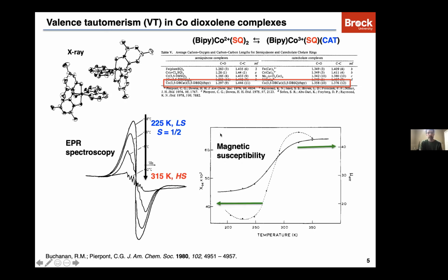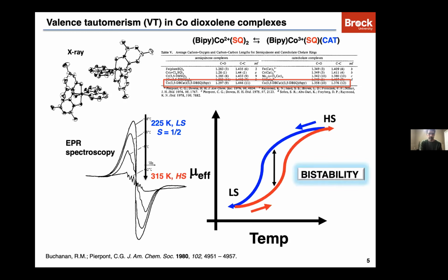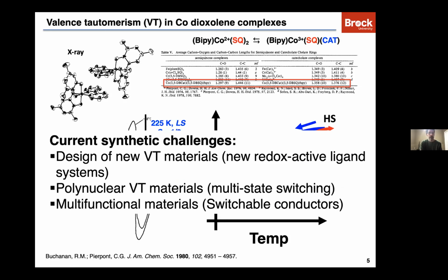Of course, you can track valence tautomerism, measuring the temperature dependence of the magnetic susceptibility. And if you have systems where there are significant intermolecular interactions, you can have bistability in the magnetic properties. So even though these valence tautomers have been known for several decades, there's still a lot to be learned about them. And there are, I guess, at least 3 current synthetic challenges that I see in this area.